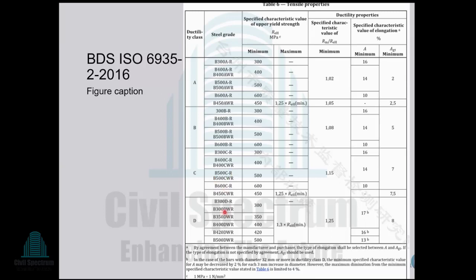B500C, B500D. So B500C corresponds to ductility class C, where the ultimate strength by yield stress ratio is more than 1.15 but less than 1.25. And for ductility class D, the ultimate strength by yield stress ratio is more than 1.25 for B500D or 420D. So this letter C, D, they represent ductility class.